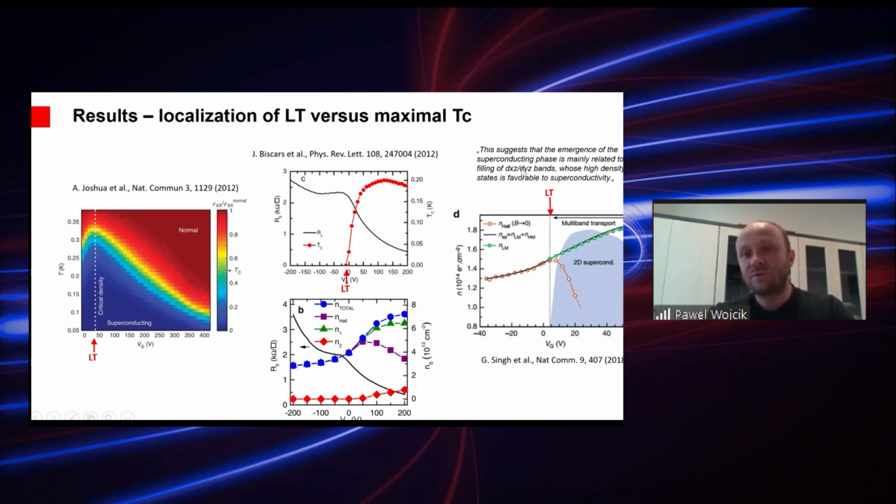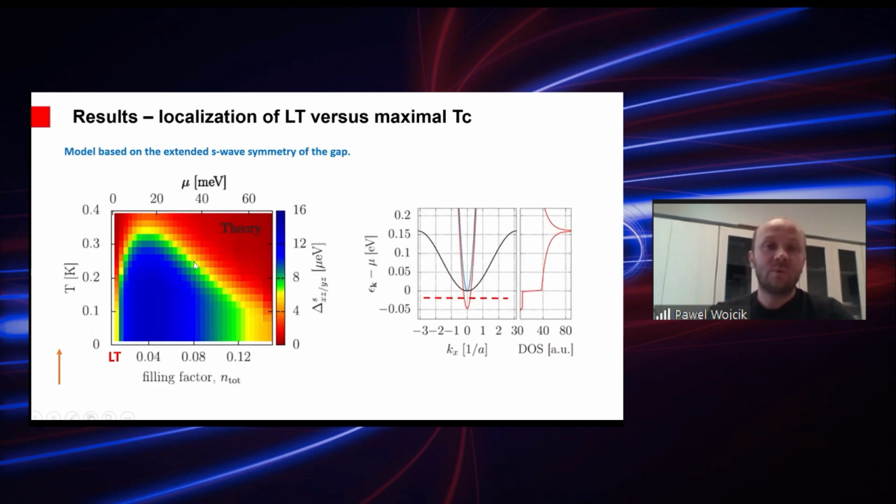In this paper, the authors even wrote that probably the superconductivity is not related to the lower lying XY band, but this superconductivity is induced by the higher lying bands dxz and dyz. And if you look at the results from our theory, you can see that it's exactly what we have in